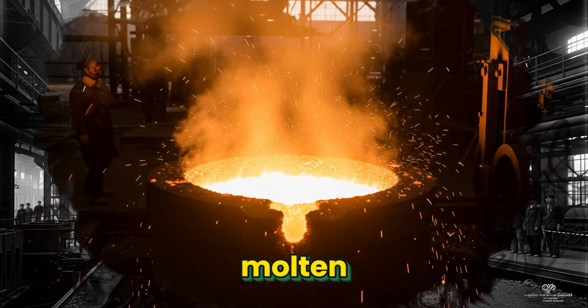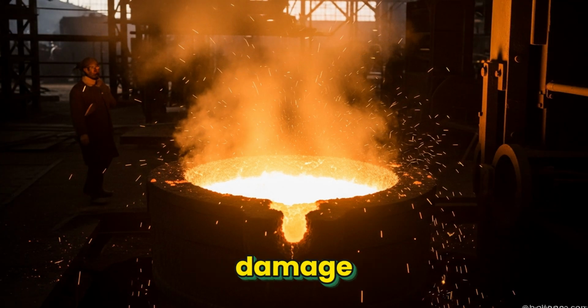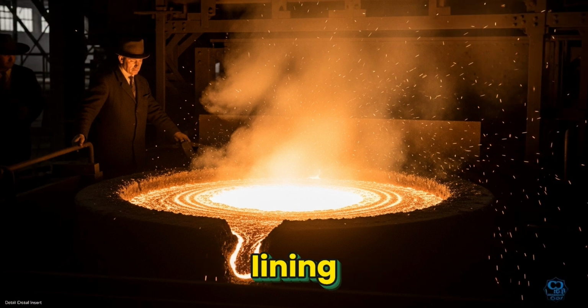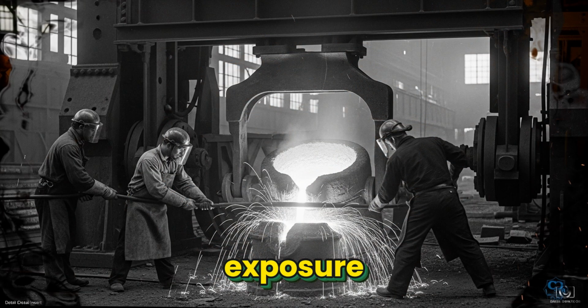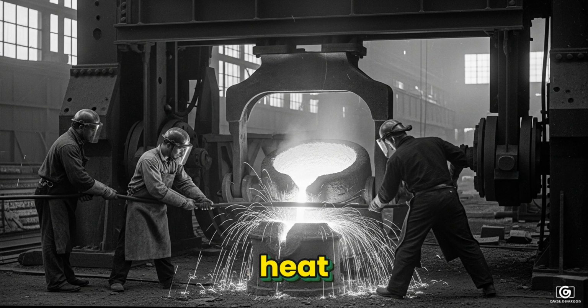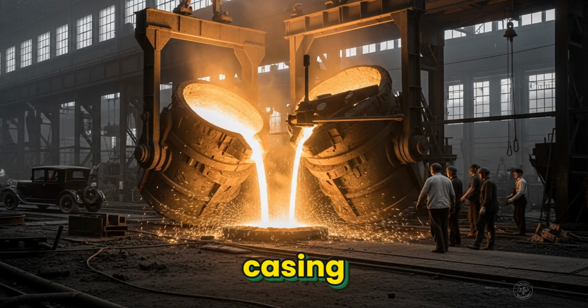Inside, the molten iron itself accelerates the damage. Liquid metal erodes the protective refractory lining designed to shield the outer structure from direct heat exposure. As that lining thins, heat penetrates deeper. Eventually it reaches the steel casing. The outer wall begins to weaken from within.